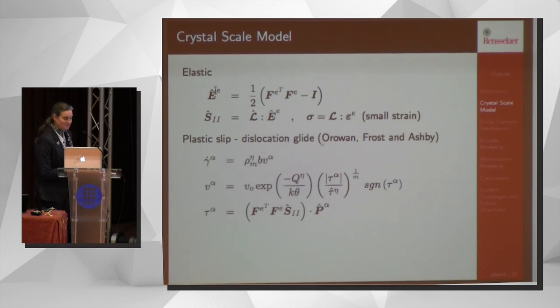So really, dislocations are the heart of everything in plasticity, at least when you're looking at crystals. And so I start with Orowan's equation. The rate of shearing on the slip system is the mobile dislocation density, rho m, times the Burgers vector for that dislocation type, times the dislocation velocity on that slip system, v alpha. That's an average dislocation velocity.